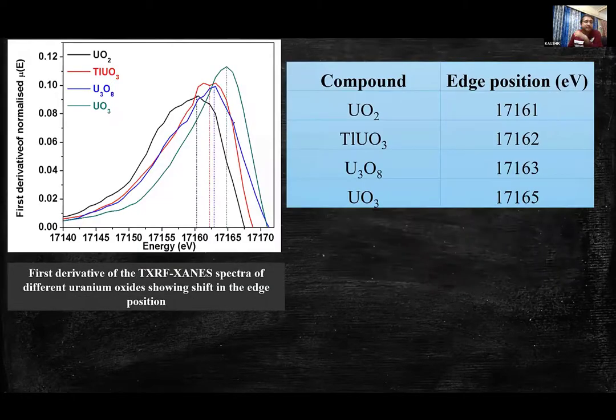Now to exactly determine the edge position, we have to take the first derivative of this XANES spectrum. This is the first derivative, and from the peak of this curve we can get the edge position. You can see these are the edge positions of these compounds along with U3O8. The U3O8 edge position is situated around uranium plus 5 and uranium plus 6, which gives us the initial impression that the uranium in U3O8 could be in the plus 5 and plus 6 states.